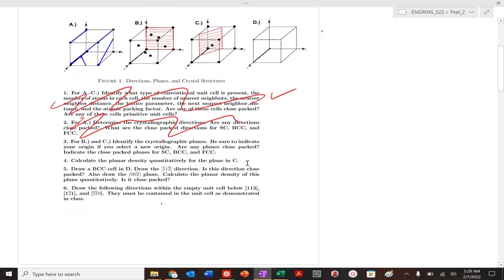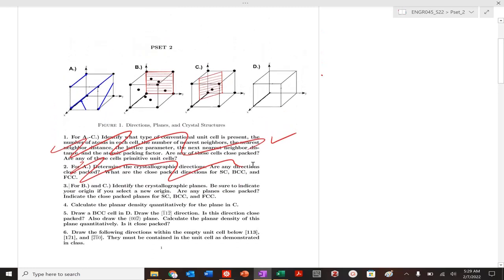All right. Identify the crystallographic planes. So here we go. I'm going to set my origin here. This plane will now be -1, the intercept is -1. I take the inverse, because x positive, x negative, and then the rest of them are all going to be 0, 0. For here, I'm going to keep my origin. What's my intercept? Well, x is going to be a half, y is going to be a half, z never. So my plane is 2, 2, 0.